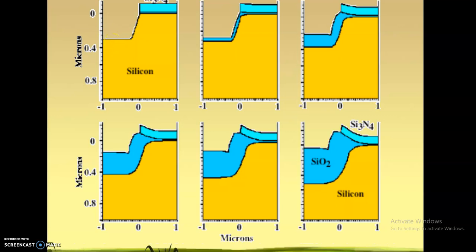Here is a closer look at the field oxide growth. This shows step-by-step how the field oxide is being grown and increases in thickness. There was a thin layer of pad oxide between the silicon nitride and the silicon. The field oxide connects with the pad oxide already present, pushing the silicon nitride up. In the final figure, the shape of the field oxide looks like a bird and it has encroached into the active region.